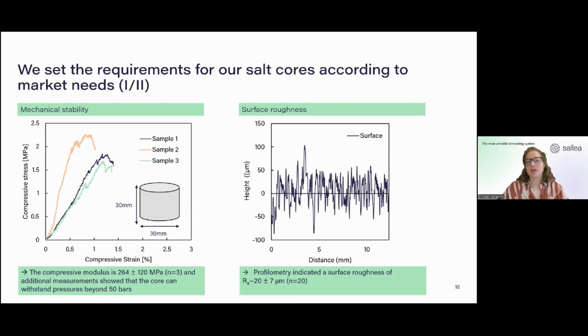Secondly, surface roughness. This is always a topic both in 3D printing, but also in composite manufacturing. And it's something that we have also been looking at, and we are still working on and improving. Overall, we did some profilometry measurements, and this indicated that we have a surface roughness of an Ra value of roughly 20 microns, which is in line with the binder jetting process. Of course, this is something that we are working on improving and lowering.